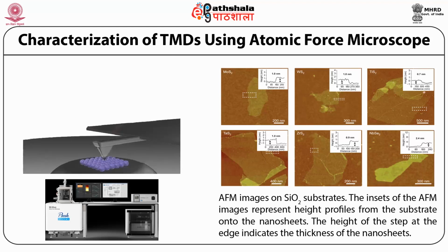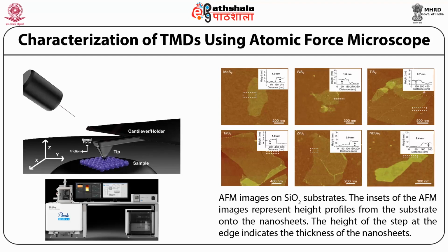However, discrepancy arises from differences in interactions of the tip with the sample and substrate. For example, the thickness of a single layer can be better determined by measuring the height of the second layer on a first layer rather than the height between a single layer and the substrate, because in the former the tip-layer interactions are constant.